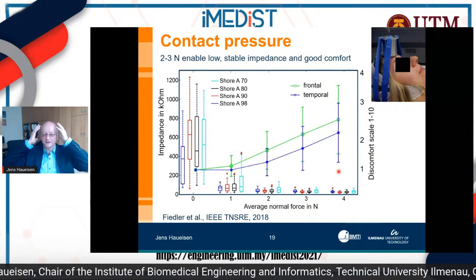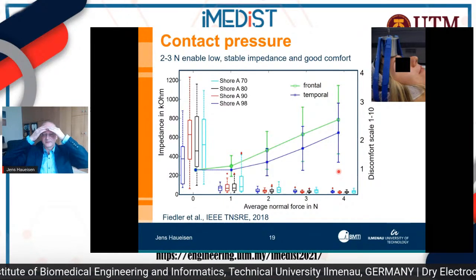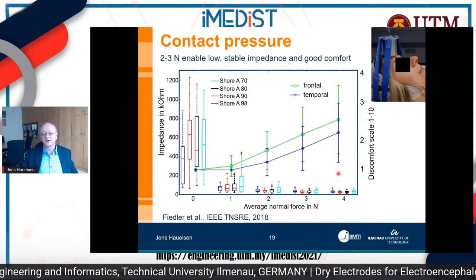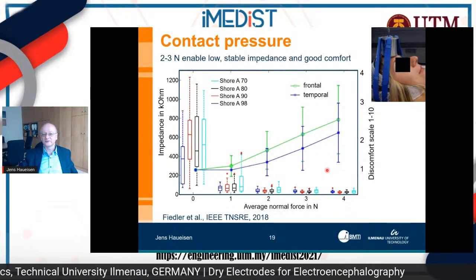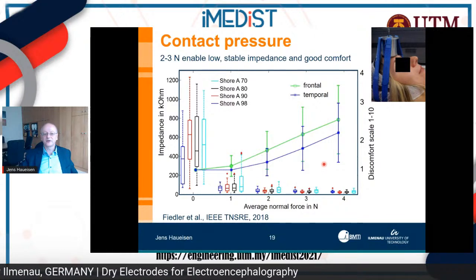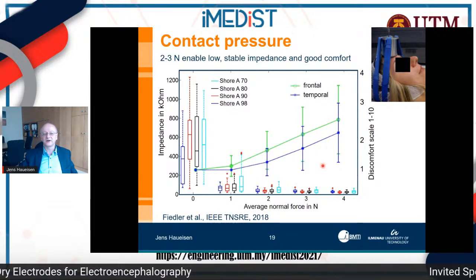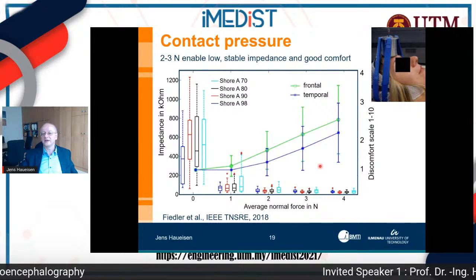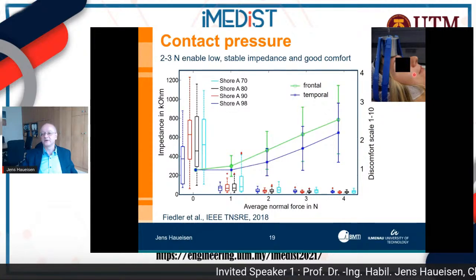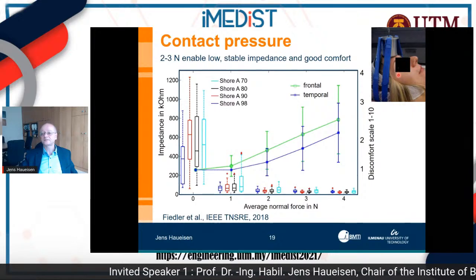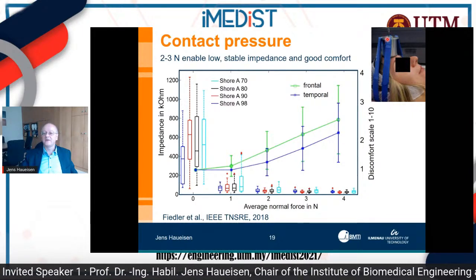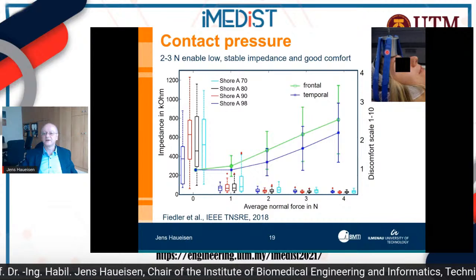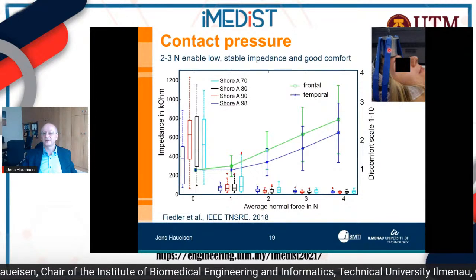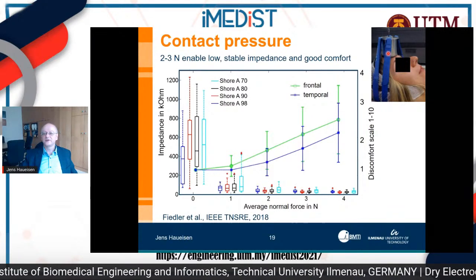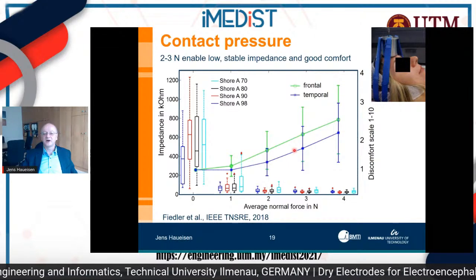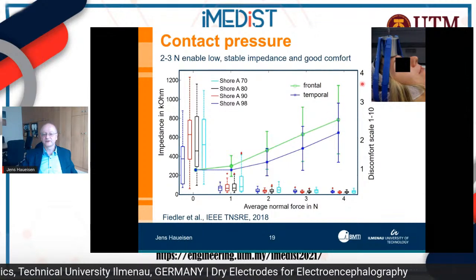So especially in the temporal positions, people were complaining, sometimes also in the frontal positions. So we have chosen to actually measure the pressure and see how the pressure and the contact impedance actually are related. And this is what you can see here. So you see one of our volunteers laying on the back and having this force measurement device here on the front part of the head, and there is an electrode in here. And then we adjust the force basically and see how the comfort is behaving. And this is what you see on the right scale.